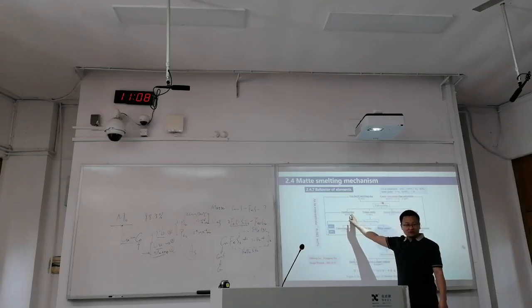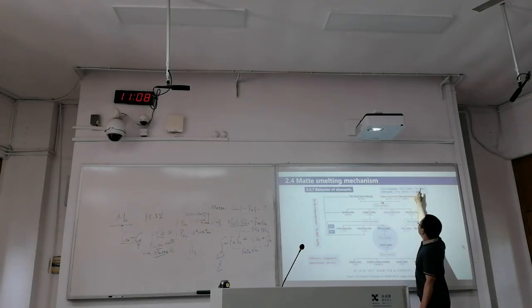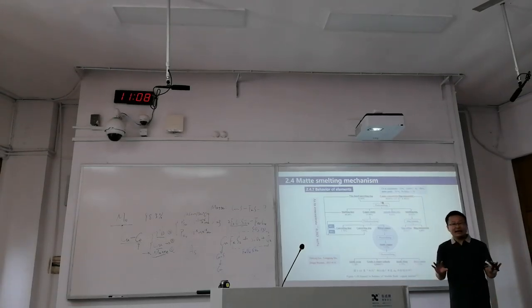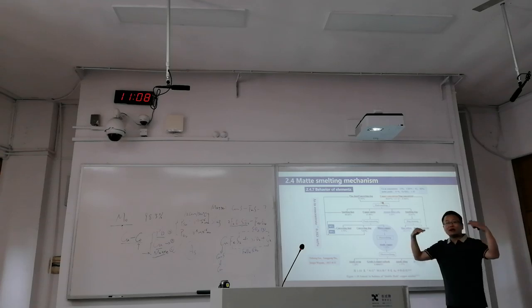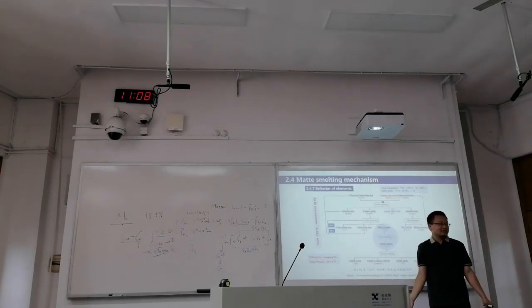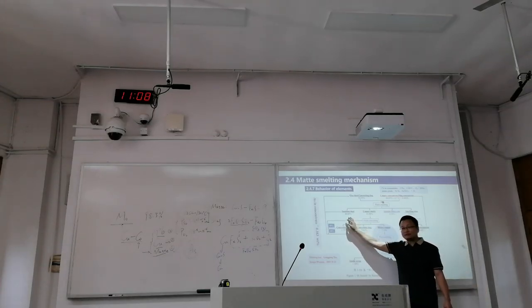Reasonable? Yes. This is the high temperature, with oxygen. Oxygen, high temperature. So arsenic and its compounds should vaporize. So this is in the smelting dust. So we are knowing that. Okay. So besides smelting dust, it's not 100%. There should be some other chemical reactions, as discussed later.